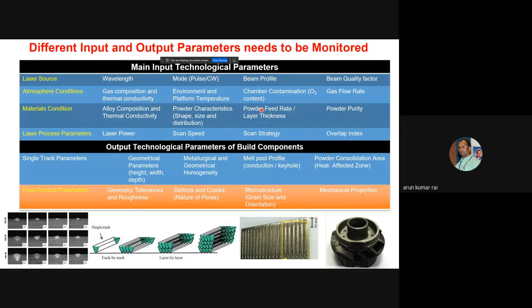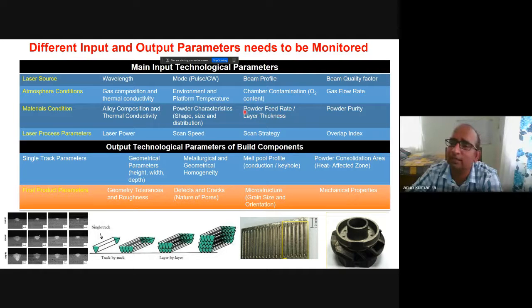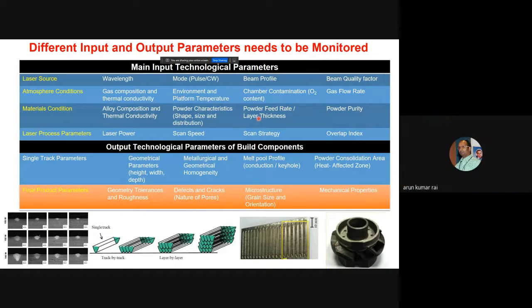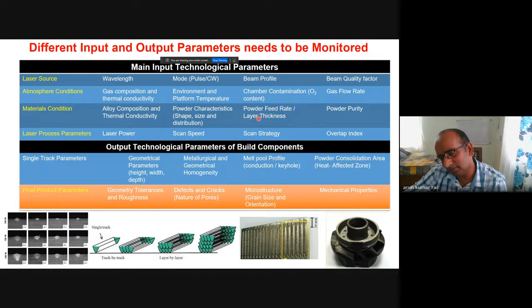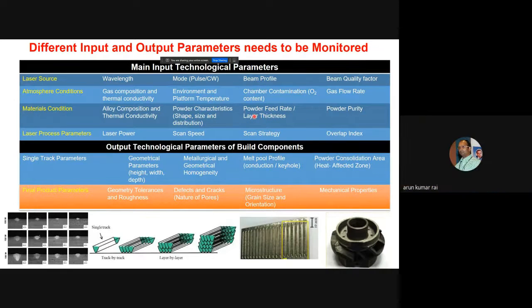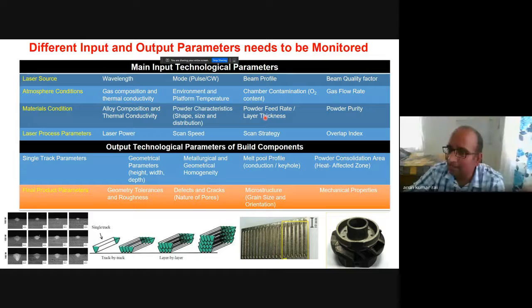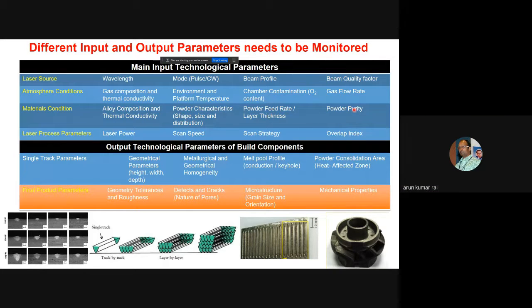Similar thing if you go to laser powder bed fusion technology. There, since you are overlaying the powder over the substrate, the thickness of the layer also decides. Suppose you are using a very thin layer, again the melt pool dynamics may be difficult, meaning turbulent, and that can lead to non-uniform deposition. And if you use a very high thickness, again this will lead to unmelted powder particles, and that can lead to porosity formation.